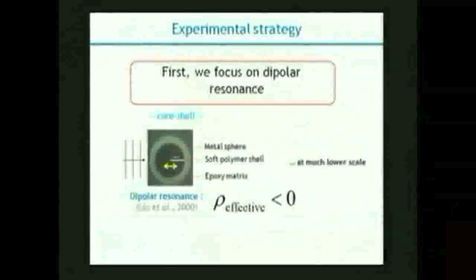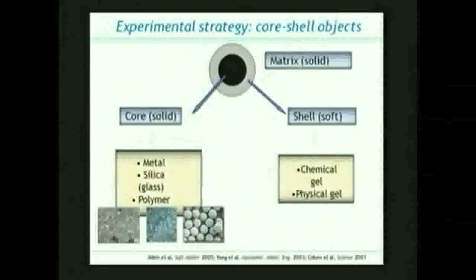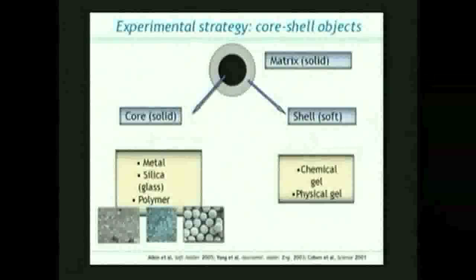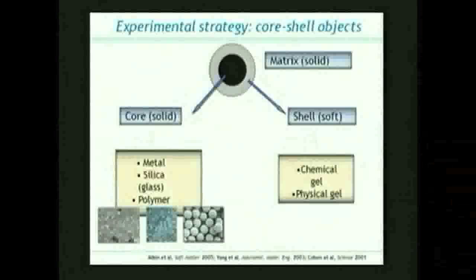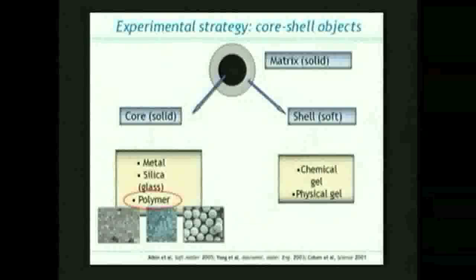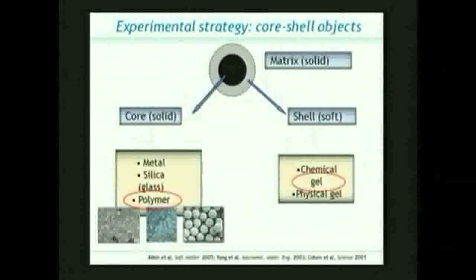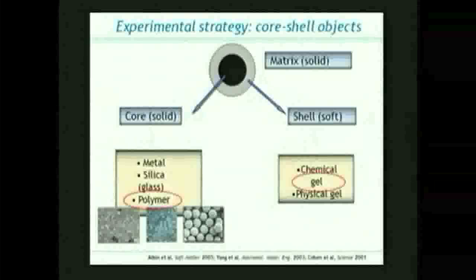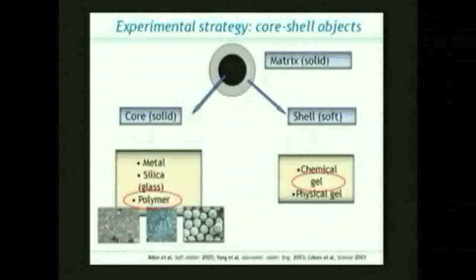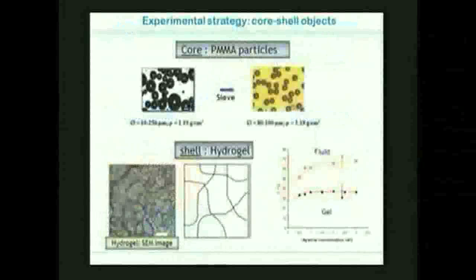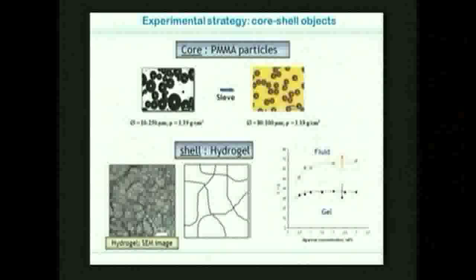So for this, we are going to try to make some core shell objects, and this core shell object will be constituted of a small hard core, a soft shell around this core, and then it will be embedded into a solid matrix. Okay? For the core, the first choice that we have made is to use polymer particles, and we're going to put this polymer particle into a soft shell which will be made of a physical gel. Yes, this red circle should be on physical gel, I'm sorry. Okay, and so for the core we're going to use PMMA particles.